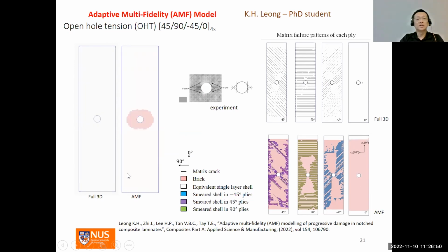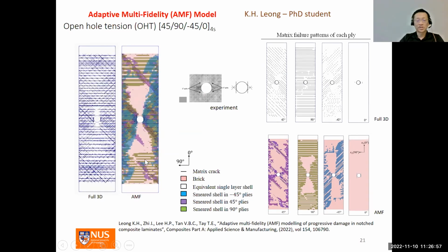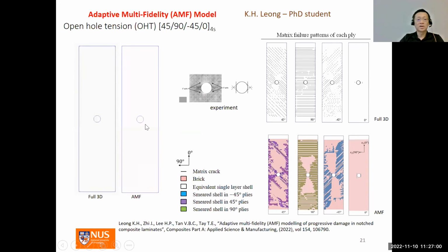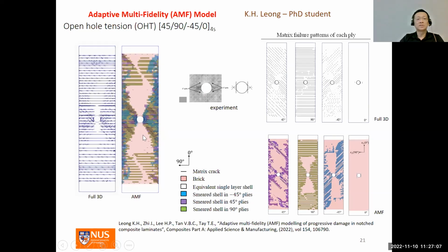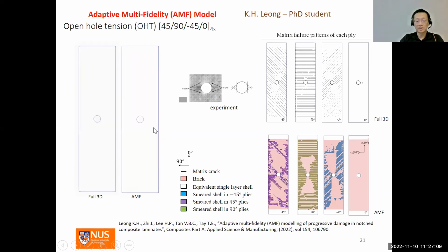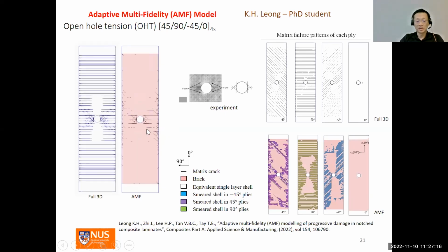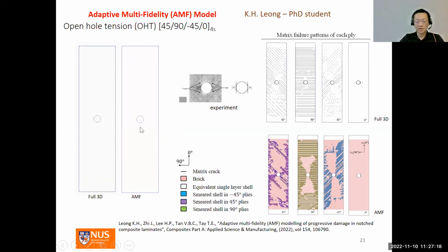However, initially the elements in the white region here are all shell elements. And then when damage is predicted to occur around the hole, the shell elements are converted, transited into 3D brick elements denoted by the pink region here. Then damage progression is allowed to proceed with the discrete crack modeling.